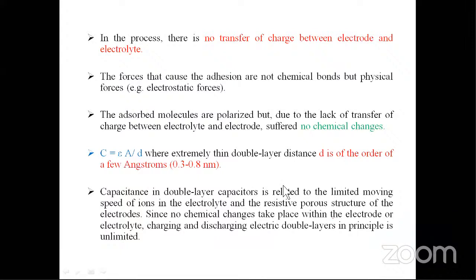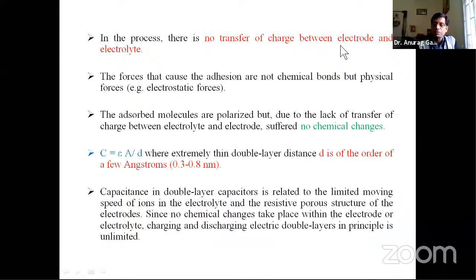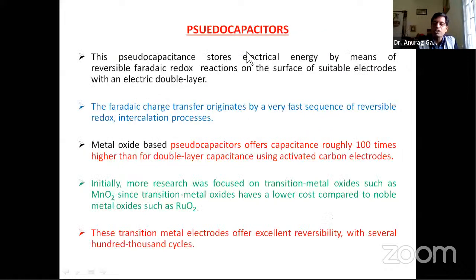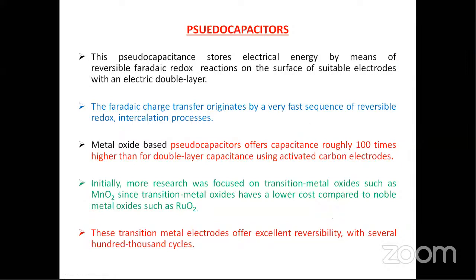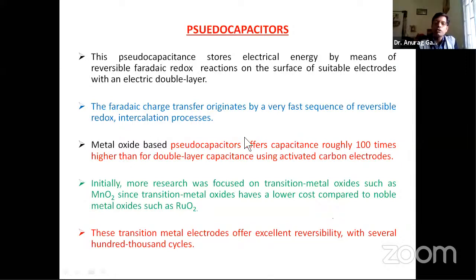But if we go to the other types of supercapacitor materials, they can have chemical charge storage, because some reversible Faradaic redox reactions take place. You see that the charge originates as a consequence of these reversible redox reactions and intercalation processes. This phenomenon is observed in metal oxide materials. That is the reason metal oxide based pseudocapacitors have capacitance roughly 100 times higher than EDLC based supercapacitors. Naturally their capacitance is high for pseudocapacitance, because they are based upon redox reactions like batteries. However, EDLCs have high power density, but their energy density is less. So that is the reason we have to work on a solution for this.